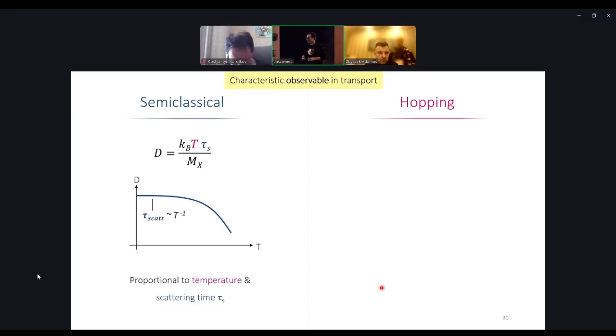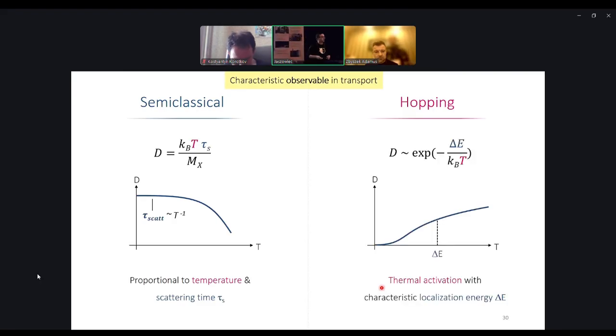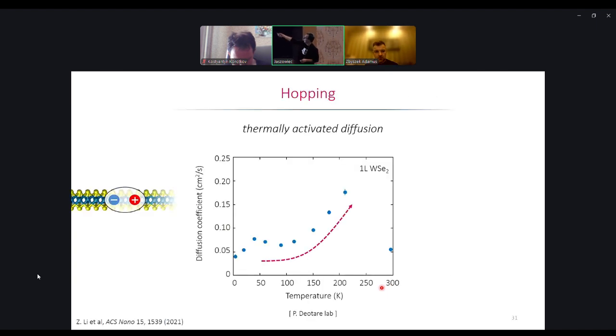So if you heat up the system, then the scattering process increases. On the other hand, here initially you have this exponential thermal activation. And this is an experimental example of hopping. This is a monolayer WSe2 with a lot of disorder, and that's what you can see. First of all, the numbers are very small, and then the diffusivity increases as the temperature increases. Yes, please.